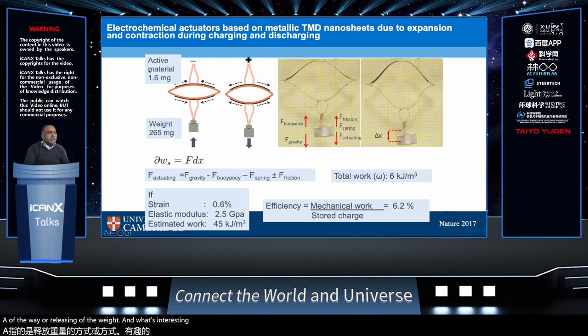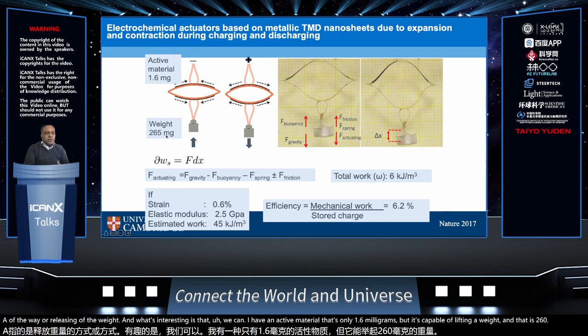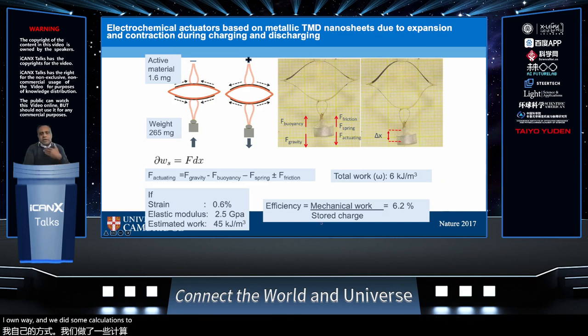And what's interesting is that we can have an active material that's only 1.6 milligrams, but it's capable of lifting a weight that is 265 milligrams, so over 150 times its own weight. And we did some calculations to understand the amount of electrochemical energy that's converted to mechanical work, and we can achieve efficiency values that are quite reasonable. The main challenge with these types of actuators is that this is all done immersed in an electrolyte, right? So for practical robotics and other devices, one would have to come up with a solid state electrolyte that would allow us to exploit this actuation mechanism outside of the liquid.